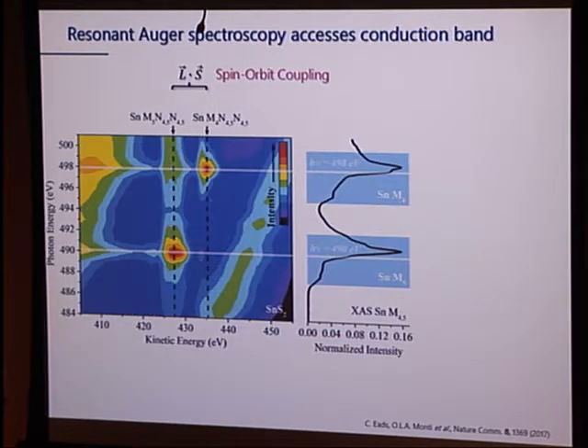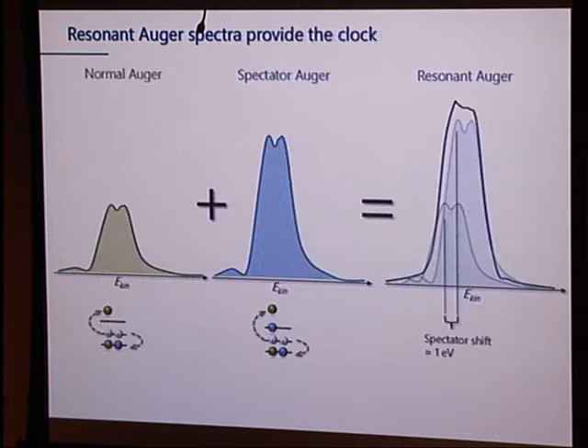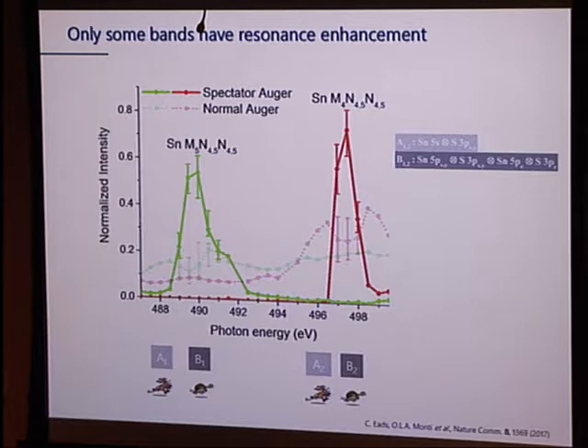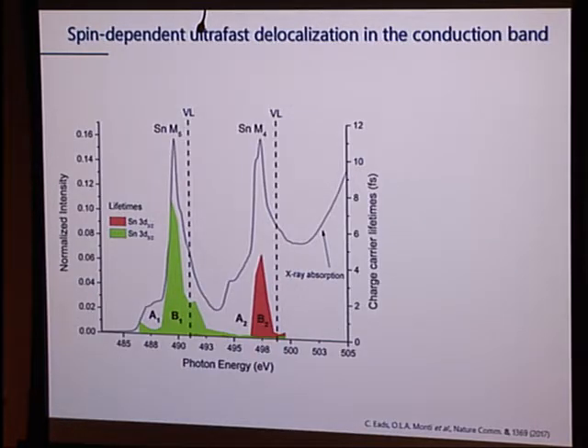I will not tell you all the details. This is sort of what the data looks like. You go to a synchrotron to do that, and you spend happy sets of 24 hours getting all that data. And when you do that and analyze it all, ultimately here is what you get. What I'm showing you here is the X-ray absorption spectrum in gray, and then the extracted lifetimes as a function of energy. All you need to know is that we have the conduction band minimum, where A1 is, and then we have points away from the conduction band minimum, where B1 is, energy-wise.